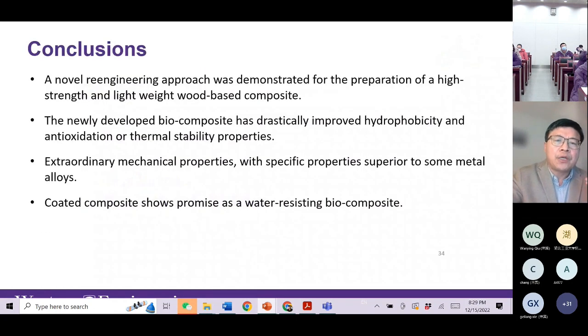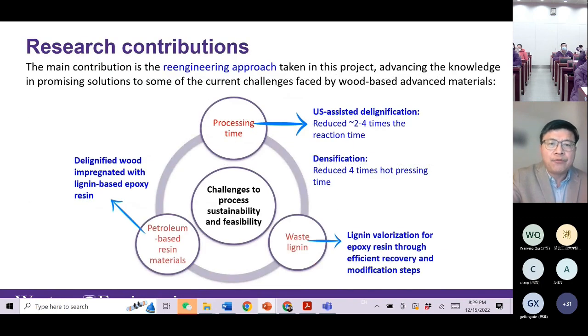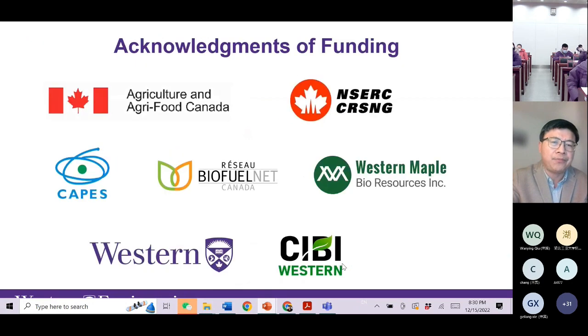The conclusion is that we achieved this novel process to produce stronger and lighter materials, and we can use that for many applications, for structural applications. Compared to the literature, we addressed these challenges, and we make this process a shorter time, and we utilize lignin, and we reduce the use of petroleum-based resin.